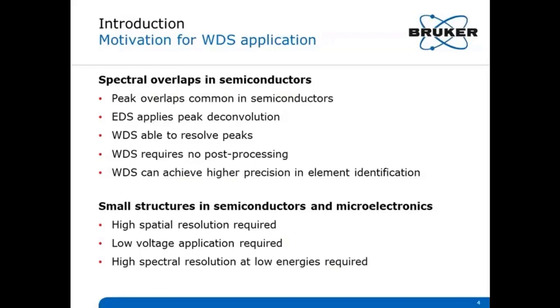WDS can achieve a higher precision in element identification and quantification. Since many structures in semiconductors and microelectronics are very small, a high spatial resolution of the analysis is required. To achieve this, low voltage has to be applied to the analysis. And that in turn requires the ability of high spectral resolution at low X-ray energies. The QUANTAX WDS for SEM is ideal for applications like these.